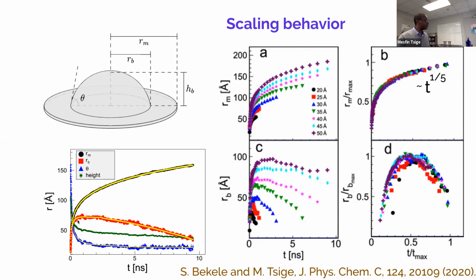This is the height, the green one. Initially it decreases significantly, and then slowly decreases, similar to the bulk radius. The contact angle drops, but then it seems to stay constant around 20 degrees. What happens is that there is a significant change initially, then that hemispherical cup stays at a constant contact angle, but just keeps on shrinking.